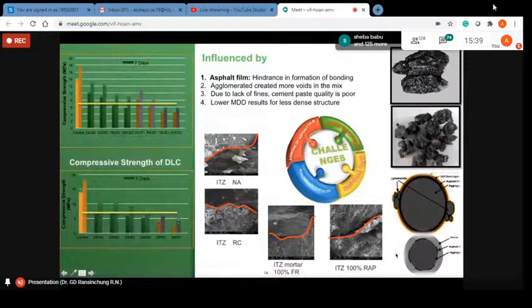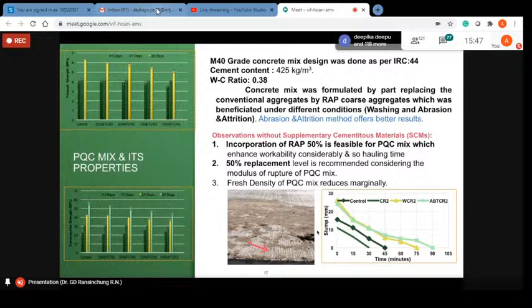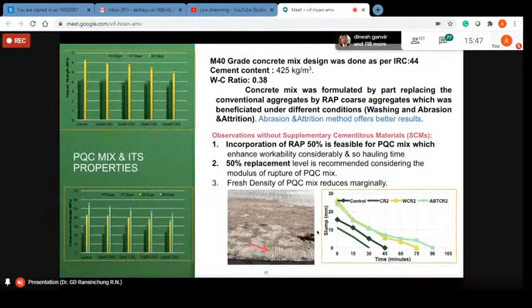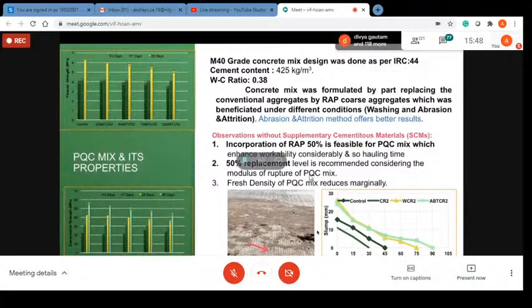The reason being, if we add more cement content in the concrete mix, there is a high chance of shrinkage cracks in the concrete matrix. So in order to avoid this kind of unwanted shrinkage cracks appearing on the concrete surface, the maximum cement content has been limited to 425 kg per cubic meter. Therefore, since our study pertains to replacement of good quality aggregates by slightly inferior quality aggregates, considering this factor, we decided to go with the maximum recommended cement content for the construction of cement concrete pavement.